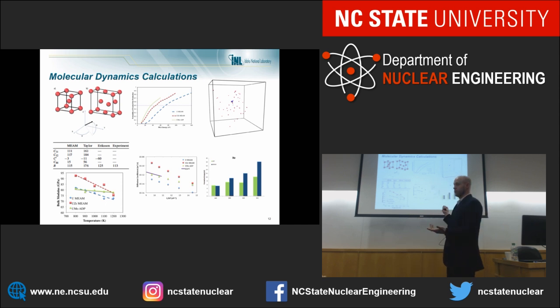So what's the number that we're supposed to use here? So we have to find either some way to narrow down what the actual displacement energy values are, or incorporate for this kind of scatter or error. Because all of these interatomic potentials can do a good job of describing the system. They're all splined to a ZBL function whenever the R is very small. So it's something going on in the intermediate distance range that yields a huge change in the displacement energy properties. So that's interesting but troubling.